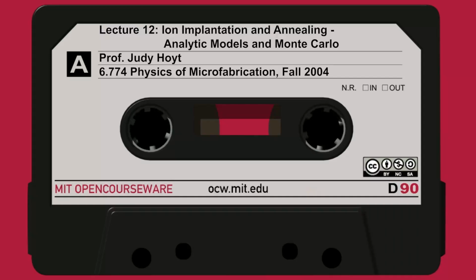We'll say a little bit more about this, but if I go back briefly to slide 8, you notice that the antimony is quite symmetrical and quite Gaussian looking. The boron profile is not so symmetrical. It's skewed. It has a larger tail region reaching towards the surface. It's got the skewness to it. And we'll talk a little bit more about why that is and how to model that.